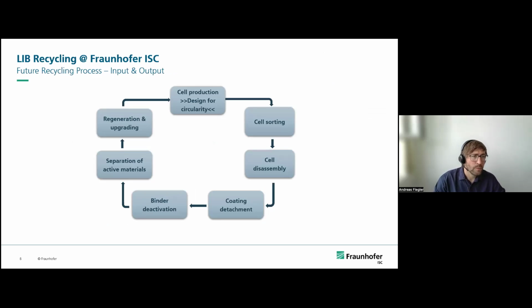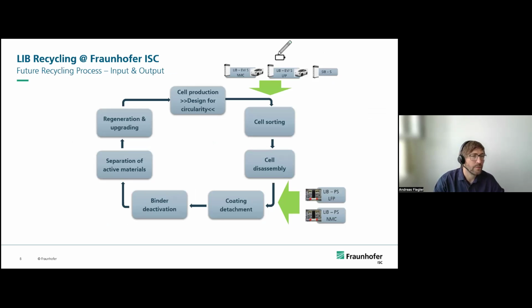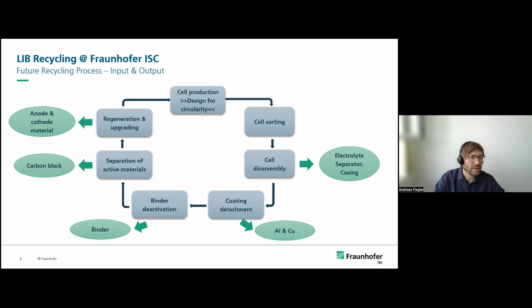Before I start, in this process we can bring the waste stream into this process, the production scrap via the coating detachment and the end-of-life cells at the beginning. And what we get out in the cell disassembly step is electrolyte, separator, and casing. In the coating detachment, the current collectors, aluminum and copper foils. Then the binder in the deactivation, and in the separation of the active materials, we can get the carbon black back, and then the anode and cathode materials after the regeneration.